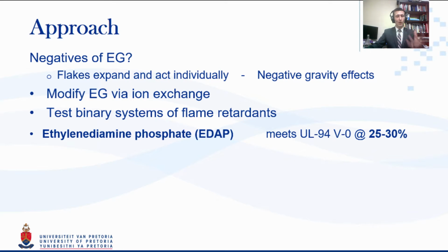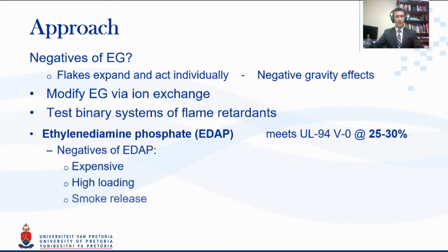What we wanted to avoid, though, are the negatives of ethylene diamine phosphate. Those being that it is a very expensive material and it requires, unless it's a spray coating, if it's put through the entire material, quite a high loading in order to meet a UL 94 V0 and good cone calorimeter results. The final and actually also very key thing is that it releases smoke that then further exacerbates the problem in these small enclosed spaces.